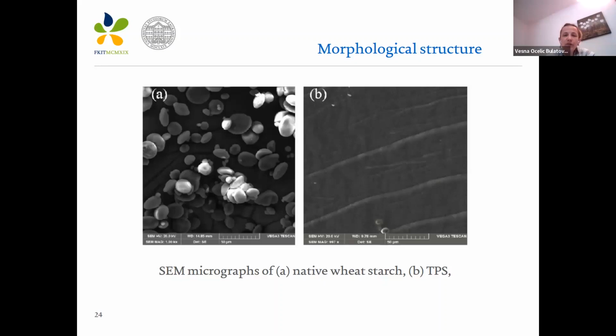The morphology of the fractured surface of TPS, as we can see, is a smooth, clear, homogeneous structure due to good dissolution of starch particles after the plastification process.